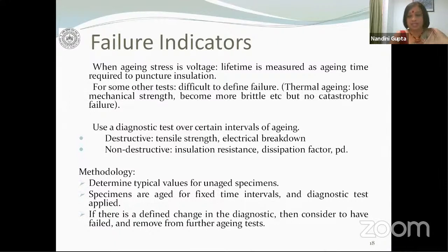Or dissipation factor increasing, maybe it has become very conductive in nature, etc. The methodology for these kinds of failure indicating tests is, you have to first figure out what are the typical values for unaged specimens. And then the specimens will be aged for fixed time intervals. And after every period of aging, a diagnostic test has to be applied. This diagnostic test could be an estimation of any parameter, maybe the PD level, maybe the resistance, whatever. And if there is a defined change in the parameter, you will have to figure out what value is acceptable, and when it crosses that acceptable value, it will be considered to have failed, and it will be removed from further aging tests. So the failure indicator has to be determined, and that also requires engineering and scientific judgment to determine what is the failure indicator, and then once this material has crossed that threshold level, it has to be removed from the diagnostic pool.